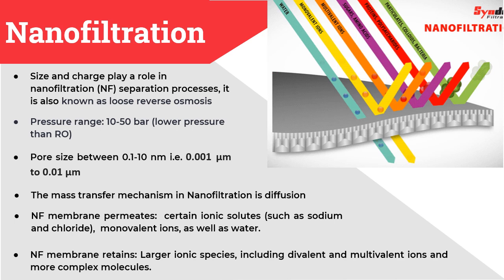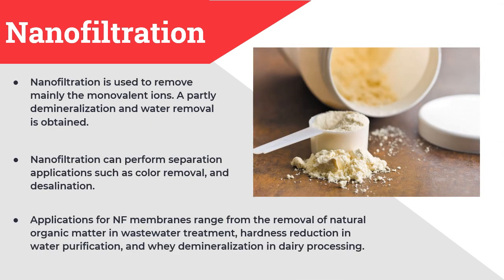Nanofiltration uses both size and charge in its separation process. It is also known as loose reverse osmosis because it operates similarly to reverse osmosis but monovalent ions may or may not permeate. The operating pressure range is 10 to 50 bars, and pore size ranges between 0.001 to 0.01 micrometer (0.1 to 10 nanometers). The mass transfer mechanism is diffusion. Nanofiltration membranes separate ionic solutes such as sodium and chloride and monovalent ions along with water, while retaining larger ionic species including divalent and multivalent ions and more complex molecules. Applications include removal of monovalent ions, partial demineralization, water removal, color removal, and desalination.